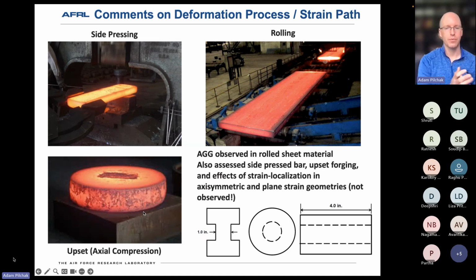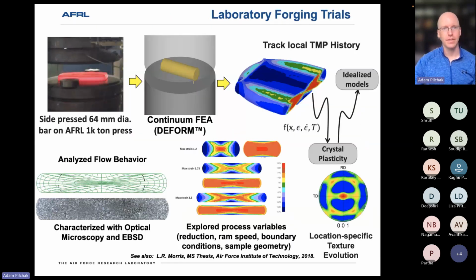We were unsuccessful in producing this effect within uniaxial compression tests, and we even made a couple of unique geometries that had reduced sections, trying to introduce shear localization to see if that had an impact. So we created this axisymmetric, I guess in cross section I-type shape, and then we also had a plane strain compression version of that, where this was extruded into and out of the page, and in neither case did we actually see any abnormal grain formation.